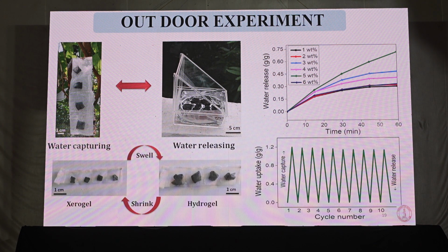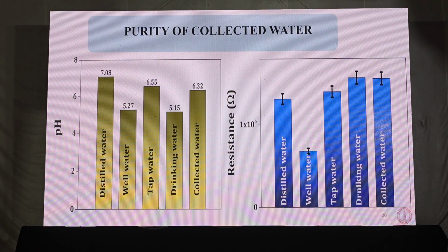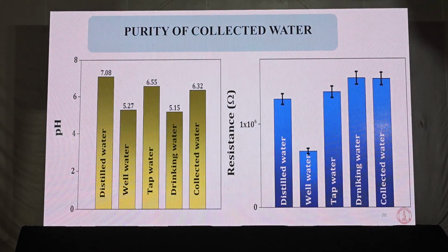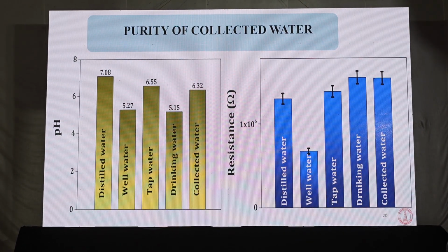In order to study the reusability of the material, we repeated 10 water capture-release cycles, and it shows good results. And in order to check the purity of the collected water, we tested the pH and the resistance of the collected water and compared it with different water samples. We obtained values comparable with drinking water. So we can say that the collected water can be used for drinking purposes.